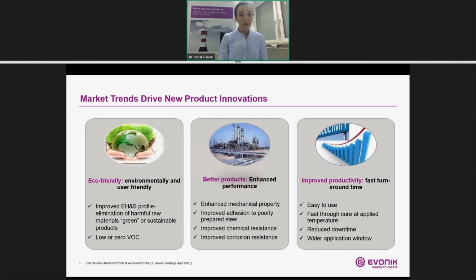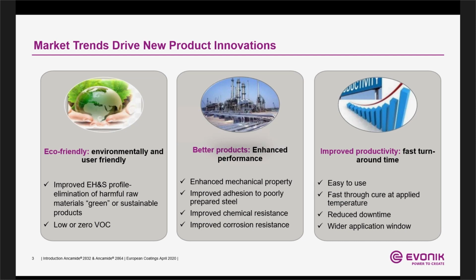If we move to performance requirements and translate this for epoxy coating, as you know, epoxy coating is used as primer and intermediate coat for metal and determines the main properties of the coating. The main role of the primer is to inhibit corrosion while providing good adhesion to metal, as well as to the intermediate coat. The intermediate coat is mostly responsible for chemical resistance and barrier properties. Additionally, it should have good adhesion between primer and top coat and deliver good compatibility to the top coat.